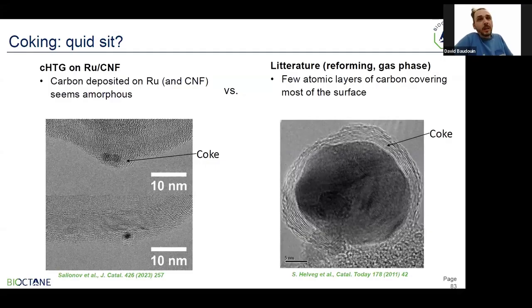Coke deposition occurs through layers, and in the worst case scenario can end up in the formation of carbon whiskers that are actually the way to produce carbon nanofiber that I presented earlier. So you have a good example on the right with these layers being formed, in this example on ruthenium. By the way, this is very particle size dependent. This occurs only above 4 to 5 nanometer particles and not below.